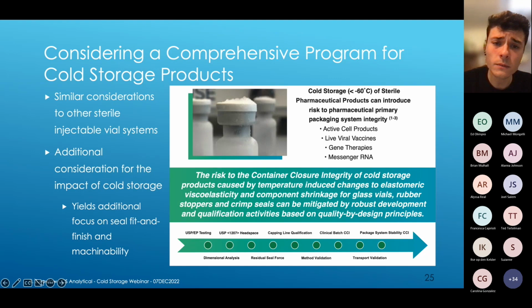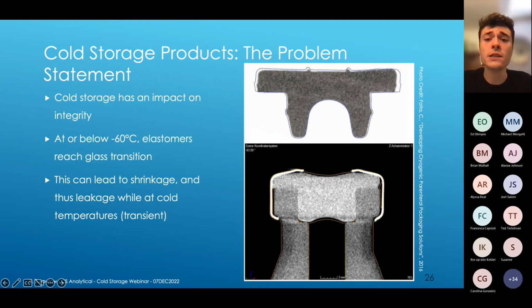And so, what is the problem? What is the additional consideration that needs to be evaluated specific to cold storage package systems? And really, it has to do, as we've touched on before, with that temperature. So at or below approximately minus 60 Celsius, elastomers that are used in a lot of traditional package systems can reach glass transition. And what this can lead to is elastomer shrinkage and thus leakage while these containers are stored at that ultra cold or deep cold storage condition that does not necessarily present itself when we're at room temperature.